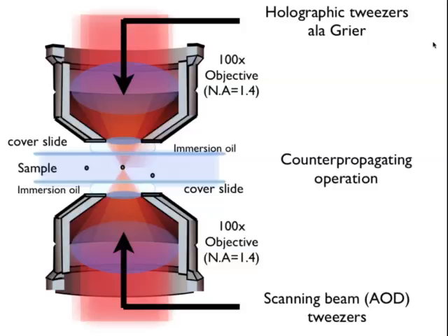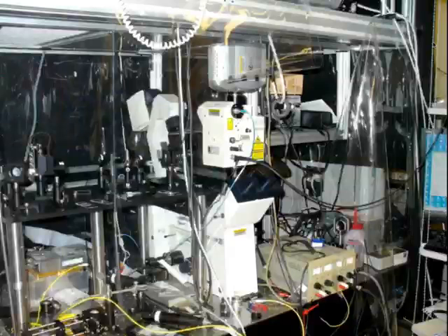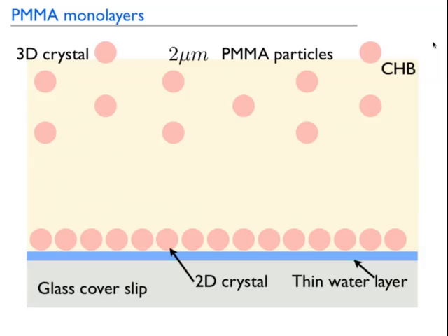So we have a system where you can have laser tweezers coming from the top, laser tweezers coming from the bottom, and from the bottom, you can also do confocal microscopy, so you can watch what you're doing while you're manipulating. I'm not going to go through what the system looks like. Here's what the system schematically looks like. If it's flat, we just take a cover slip, we put a thin layer of water on it, we should have a 2D crystal over here, we should have a depletion region, and we should have a 3D crystal over here, and this is what it looks like, right?